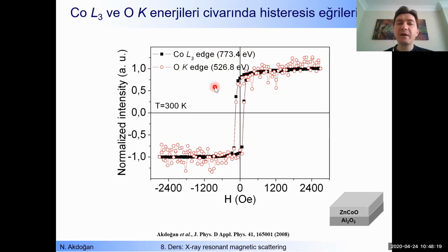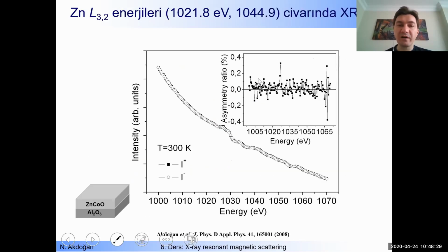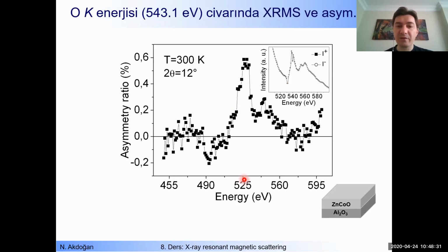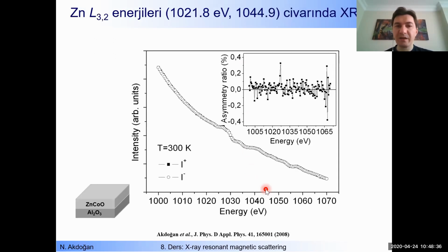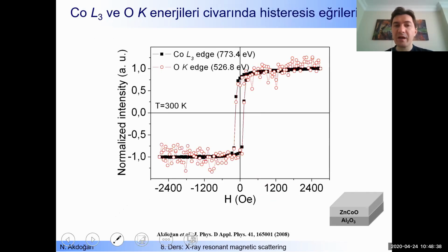And the red one is taken around the oxygen K edge, around 526.8 electron volt, around that maximum, okay? Both data are taken at room temperature, when the temperature is fixed.